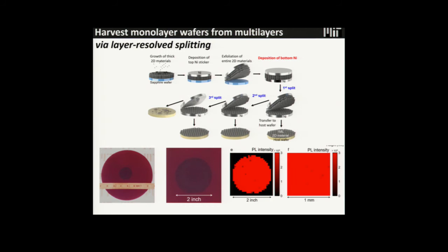Then we did some fine scans of PL intensity. I asked my student to do the fine scan on wafer scale. It takes 3 days for him to finish it, so I feel sorry for him. But anyway, we got the truly monolayer signal from the PL and boosted up the PL intensity by doing it all at wafer scale.